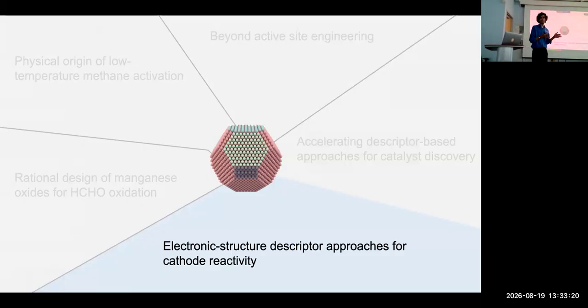Your cathode material is usually an oxide, like lithium cobalt oxide, lithium manganese, lithium nickel, so far. And the electrolyte is usually an organic molecule containing a lot of CH bonds. So we got curious about whether we could use some of the learnings here about how CH bonds break in a use case that is completely removed from what one would typically study in surface reactions.